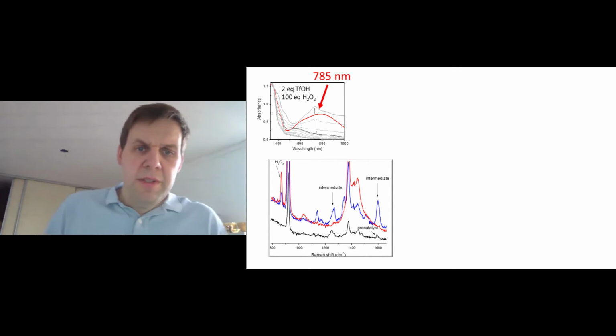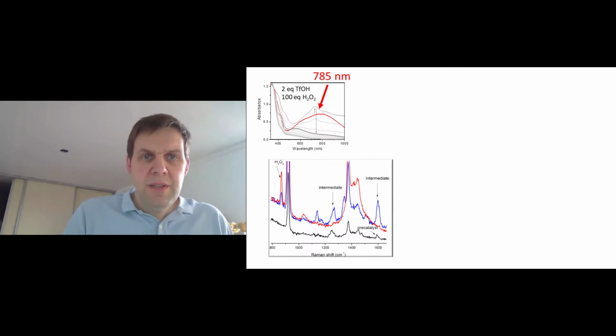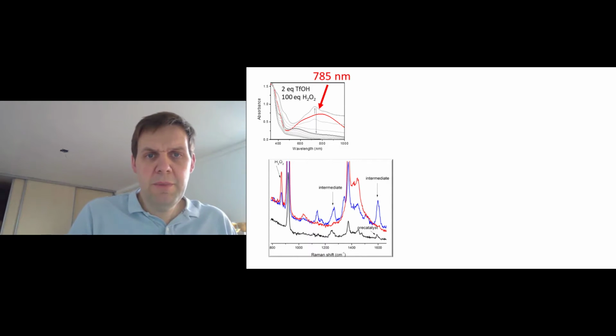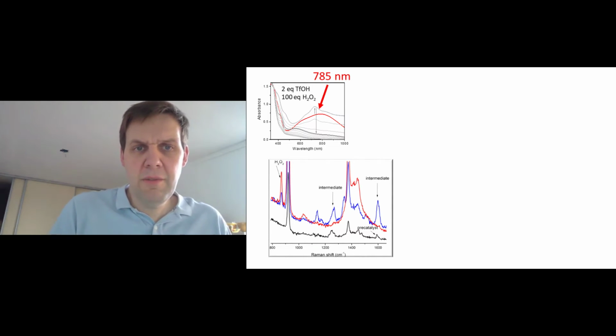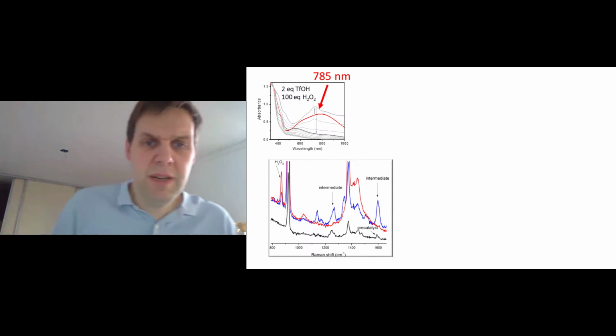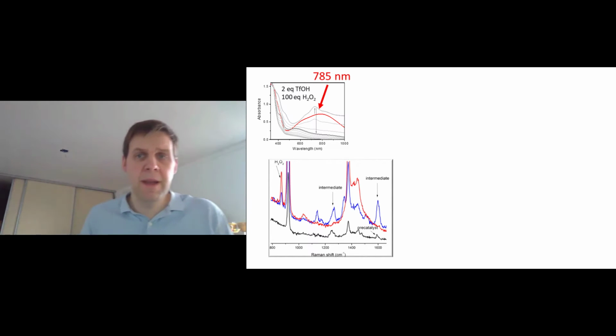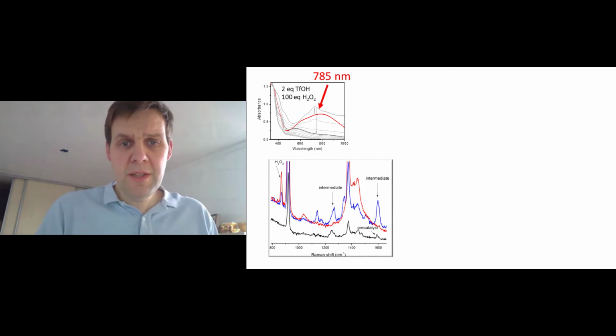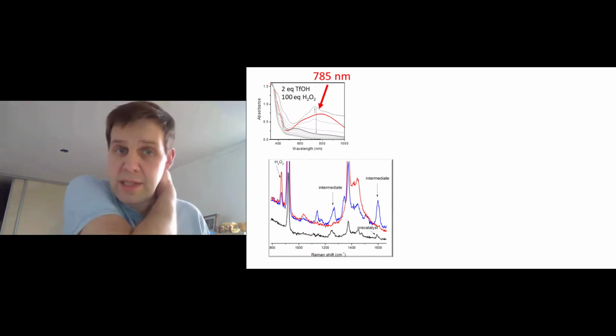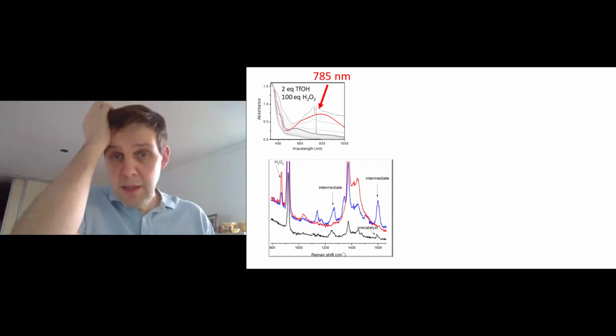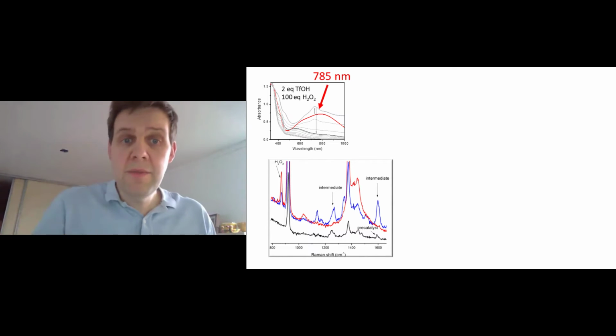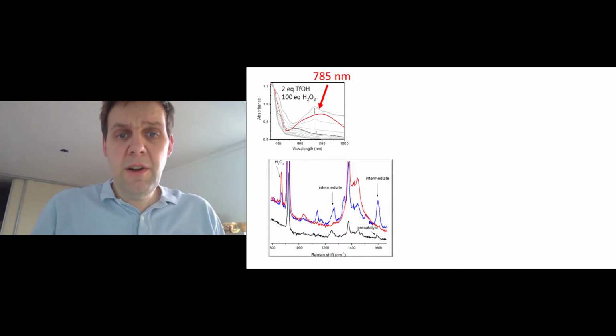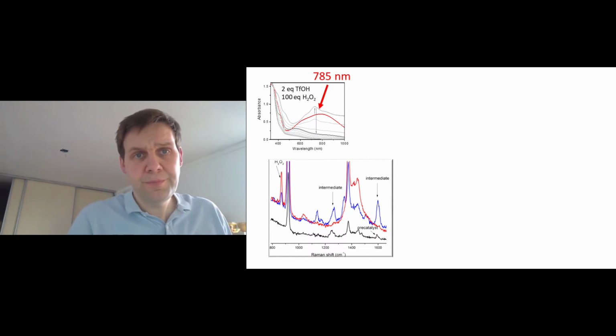So we monitor 785 nanometers, which is resonant with these very short-lived absorption bands. But bear in mind that this absorption at 785 or around 800 nanometers is only there for the first few seconds. So we have 3 or 4 seconds in which to get spectra. And we can do that. And we actually see that, well, if we look initially, we see very weak signals from our catalyst, which are resonantly enhanced. And we see a very large jump in intensity of some bands, which are in an intermediate, which are quite characteristic of a phenolate, an oxidized phenolate unit.